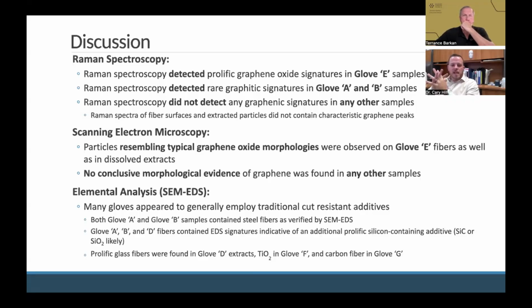To summarize what we found here, again, only one of the 8 glove samples we've tested to date has been definitively shown to have graphene or graphene oxide, any kind of graphenic content. There were, in some cases, graphitic signatures. So again, in glove A and B, B was the example that we showed earlier in the slides. If you look at the paper, I think there's some evidence in A as well, where we found sparing evidence; it was a rare occurrence that we saw these additives. And when we did, the 2D peak is shouldered, which is indicative of graphite.